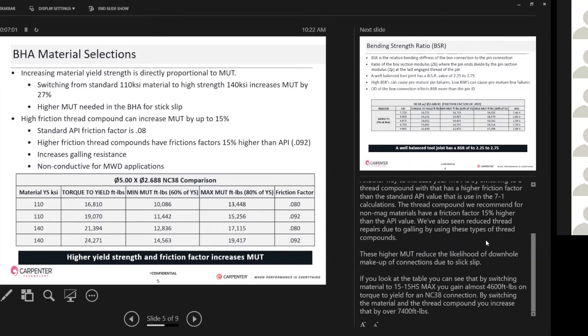If you look at the table at the bottom, just by switching to the 140 KSI 1515 HS Max, you can gain just 4,600 foot-pounds of torque to yield for a standard MC38 connection. And then if you switch the material and the thread compound, you're gaining over 7,400 foot-pounds in that same geometry, same connection.